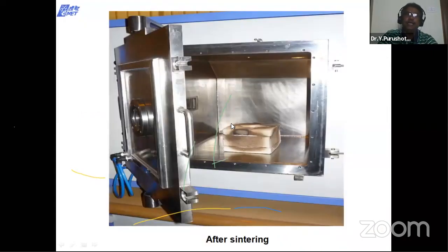And you see, after sintering, it looks like this. This is a very clean process. So inside the chamber, it will be like this only. Whereas here, this casket, a low loss insulation material, has some moisture. There are different grades; ceramic fibers are also available, for 1200 degrees centigrade, 1400, 1600 degrees centigrade. Whatever this picture shows is a 1200 degrees centigrade ceramic fiber. When we started the sintering experiment, moisture came out from this fiber. So in the first sintering, it looks black, and after two or three sintering experiments it comes back to white color, because whatever moisture was there has been removed.